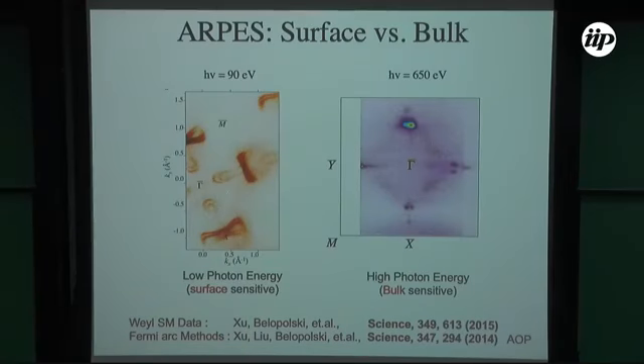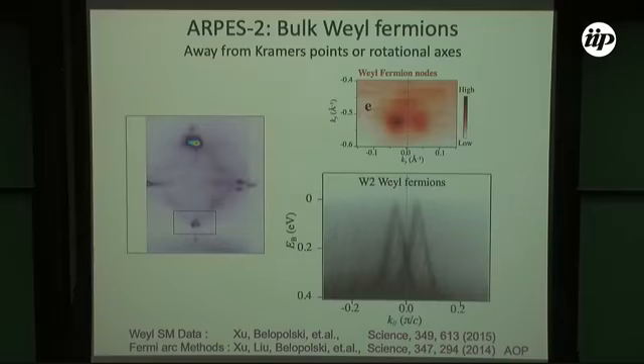Let's back out here. On the surface, we see arc-like states, though not so clear immediately. They're non-closed. But if we probe the bulk band structure deep into the sample, then we see that the Fermi surface looks like mostly two points. Certainly, it's very different from here. This is the surface Fermi surface, and this is the bulk Fermi surface. Now we can image how the surface Fermi surface evolves to bulk, or bulk evolves to surface, by changing photon energy. One of the things we want to check is, if this is our bulk Fermi surface feature, how does it behave in the energy axis?